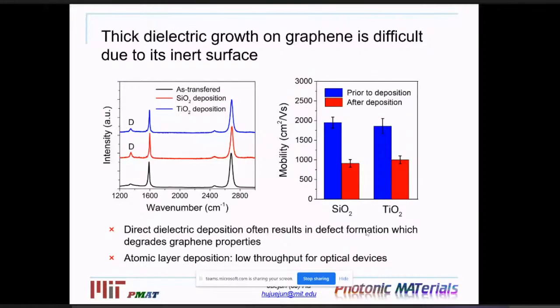So this is actually what we started out with. We tested different kinds of materials, starting with silica and titanium dioxide. They are common materials for passive photonic integration. But what we found is that if you deposit them directly onto a graphene substrate, and you look at the Raman spectra here, at the bottom, this black curve is the pristine graphene after the growth. It shows essentially a defect-free signature. But if you go through this dielectric material deposition, what comes up is this little D peak, which corresponds to a generation of defects in the graphene material.